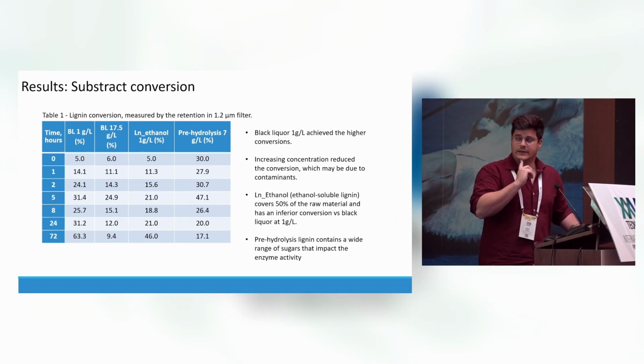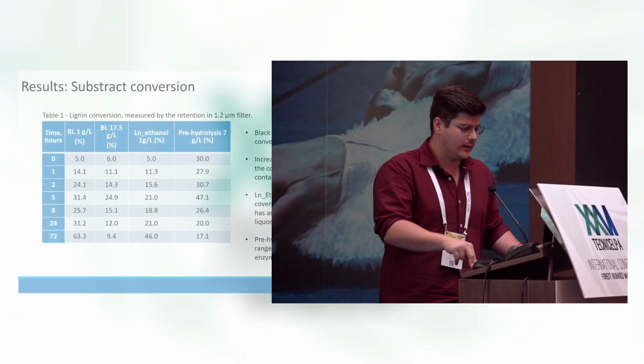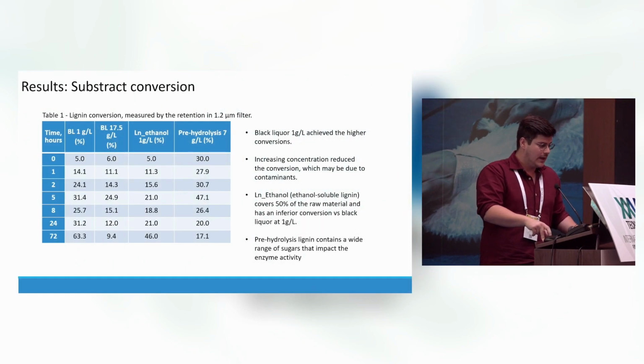And this is because of the fractionation method that we used. We solubilize lignin in isopropanol, ethanol, and methanol. And the more reactive fraction of lignin is soluble in isopropanol. So we removed the higher reactivity lignin. However, we studied the ethanol soluble fraction because it covers 50% of the raw material.